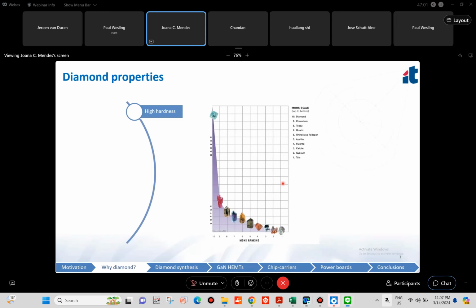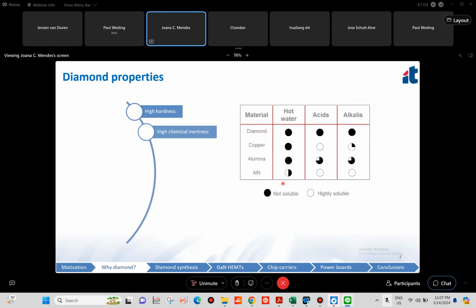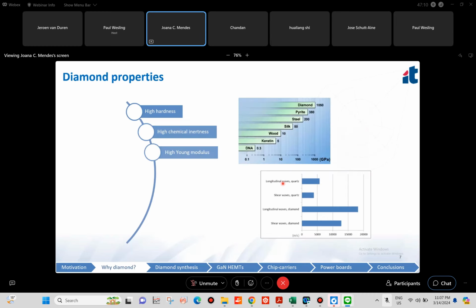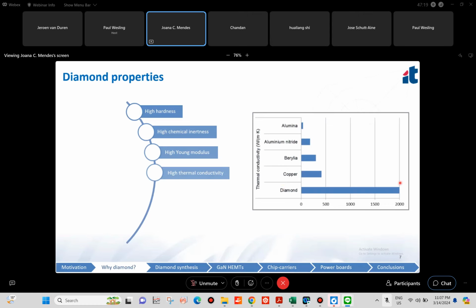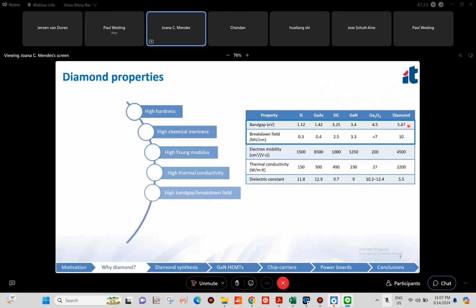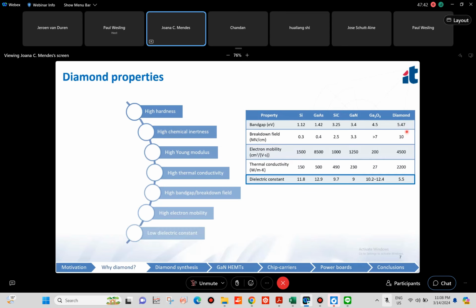So diamond is the hardest material known to man. High chemical inertness, so you cannot etch diamond with any liquid whatsoever. It has a very high Young's modulus, so it's a very rigid material and has a correspondingly high surface acoustic wave velocity. It has a high thermal conductivity, 5 times higher than copper. And it also has a high band gap and high breakdown field, so 5.47 eV for band gap and 10 megavolt per centimeter breakdown field. So this makes diamond an extremely good electrical insulator. It has a high electron mobility and it has a low dielectric constant, 5.5.